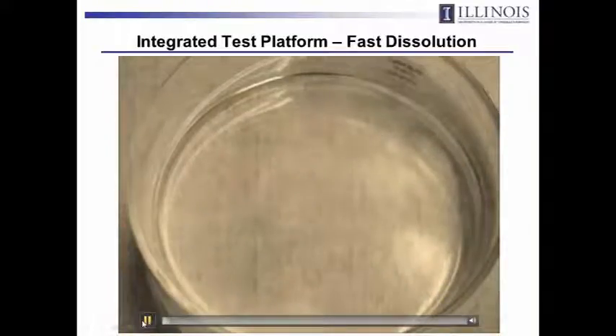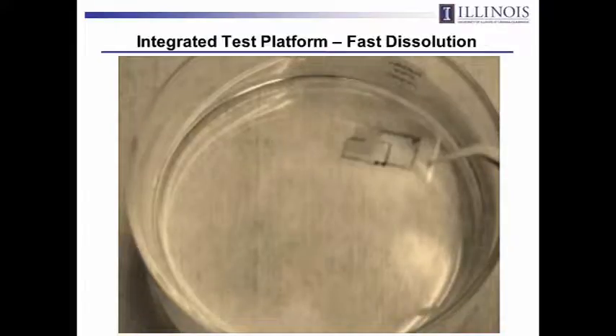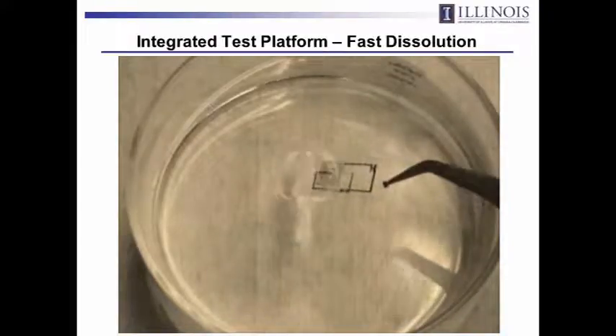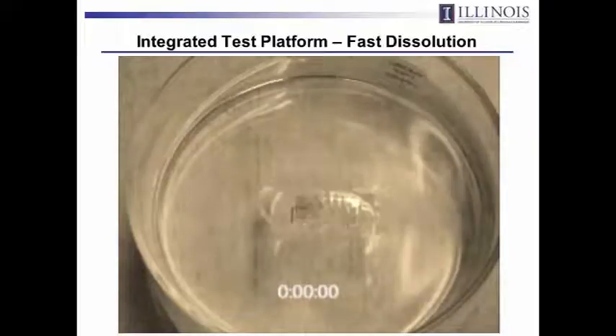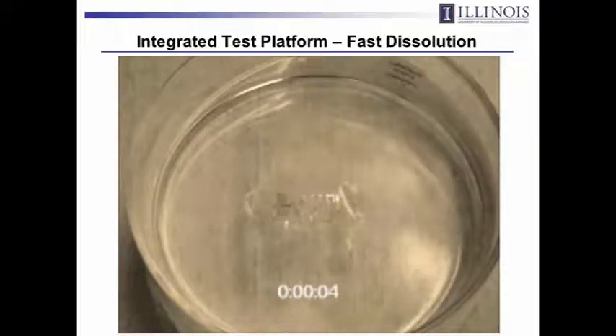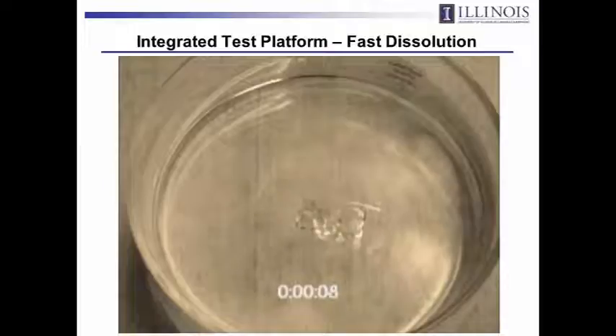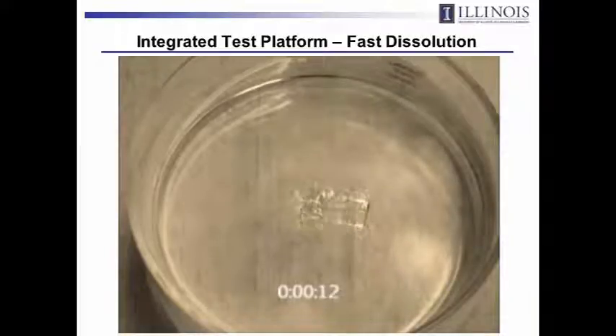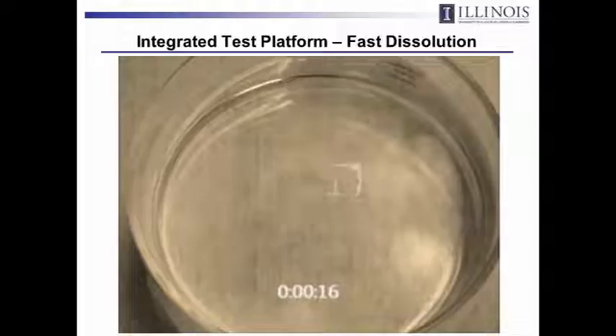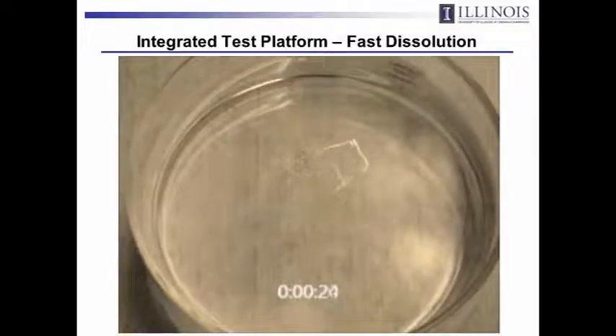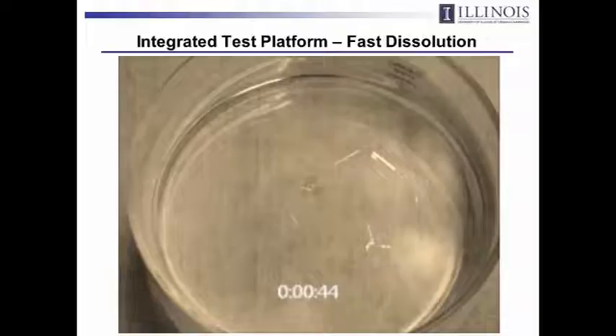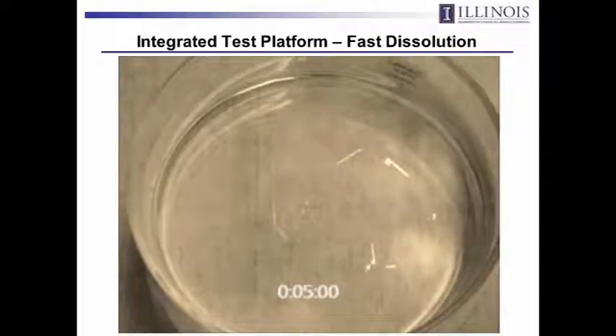This is a simple test platform, very simple circuit, like the one I showed you before. Silk is the substrate. This is just a beaker of water, a petri dish of water. And what you see here is as the circuit begins to dissolve, what disappears first is the silk. It's treated so that it's essentially in an amorphous state, so its rate of dissolution is very fast. Once it's gone, the circuit components themselves are not mechanically strong enough to hold together, so it kind of disintegrates at that point.